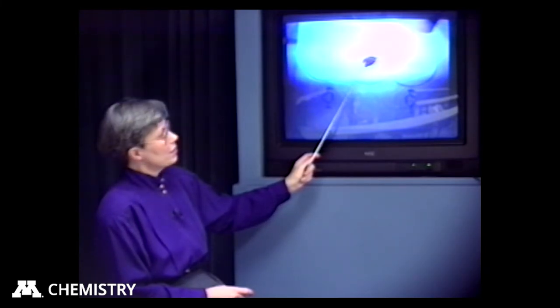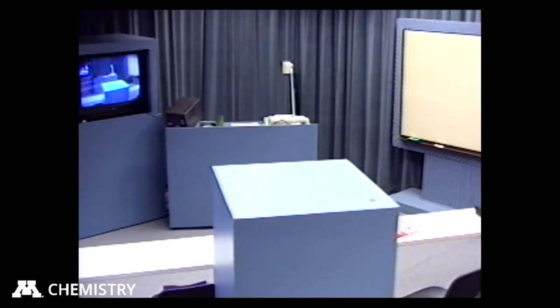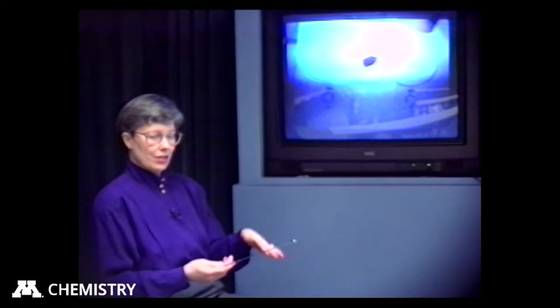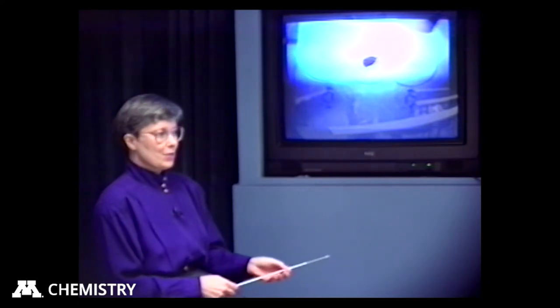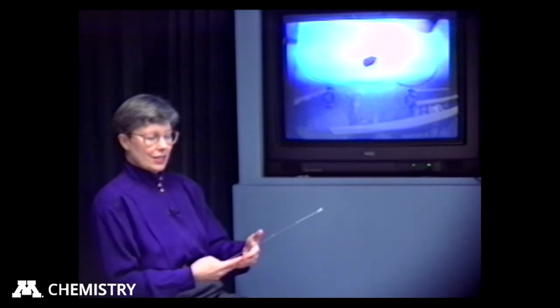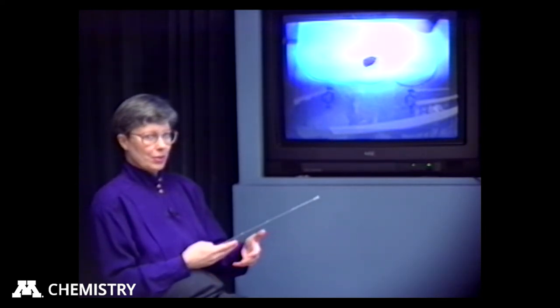The dark red color comes from charge transfer interactions, but the driving force for the change when you simply mix these two solids together is the formation of strong hydrogen bonds in the product. You can get the same crystal form by growing the red crystals out of solution. So you put the two yellow solids in solution and let it crystallize, and what you get out are red crystals. These red crystals contain both of the components, but they're hydrogen bonded together in a new way. It's really a new compound. It has a new melting point, new infrared spectrum, different colors, different optical properties, different electrical properties.